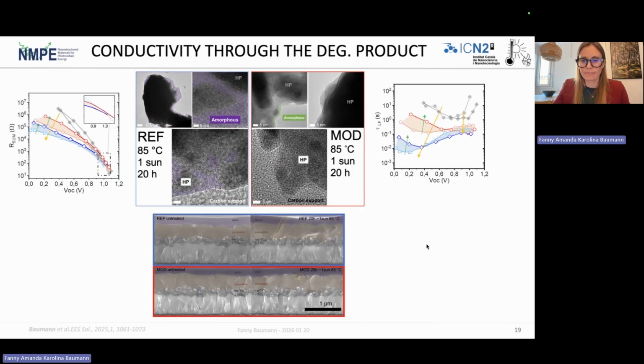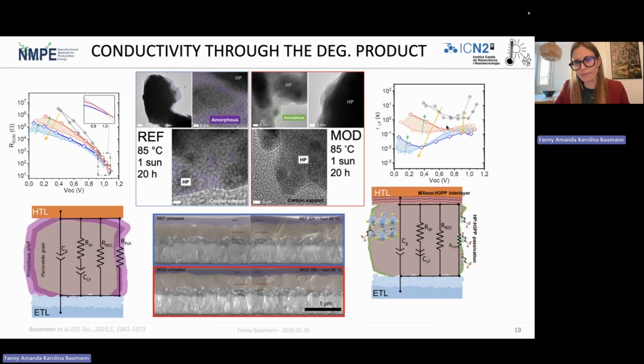So to summarize this a bit and compare it with the impedance, we can see that, well, if we have this amorphous phase forming and it has a high carbon content, it could be a very good explanation that this is responsible for the lowering of the shunt resistance. And it also seems clear that we have a general increase in the ion conductivity over time, but there's also a very large component that could be explained by a high ion conductivity in this new material.